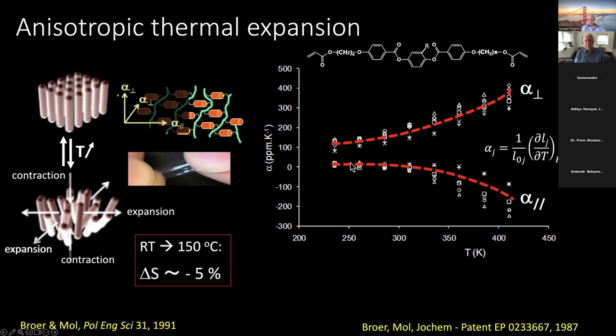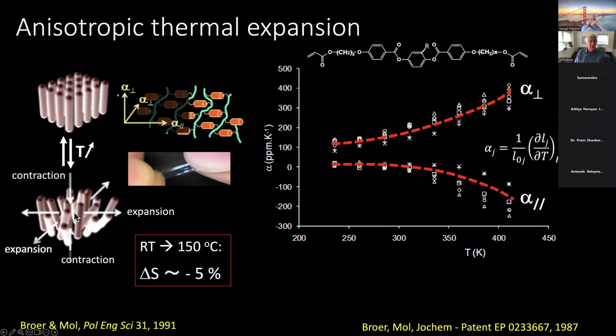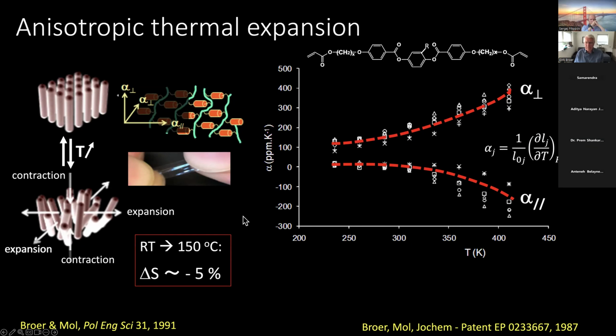The reason for this behavior is that when you are heating the sample, you go from a highly ordered state. This is exaggerated here in real time. It is not as ideal as shown here, but upon heating, you are decreasing the degree of order, which leads to a minor contraction parallel to the alignment, and expansion perpendicular to that. And only minor changes in the order parameter of the system are already sufficient to create this special behavior.